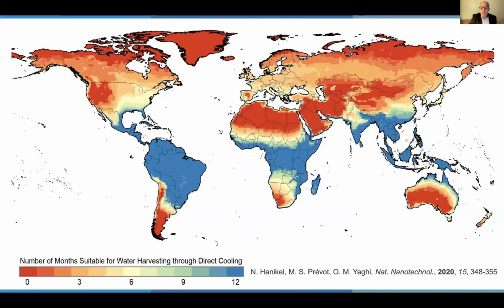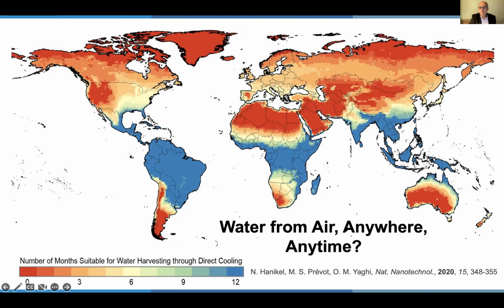So our idea has been, if you could create a material like a MOF that can trap water from air in these red regions, you would be able to trap water from air anywhere in the world, not just where it's most needed in these red areas, but also in areas such as the blue regions where there's plenty of water, but the water may not be clean. So that's our vision: to harvest water from air anywhere in the world at any time of the year.